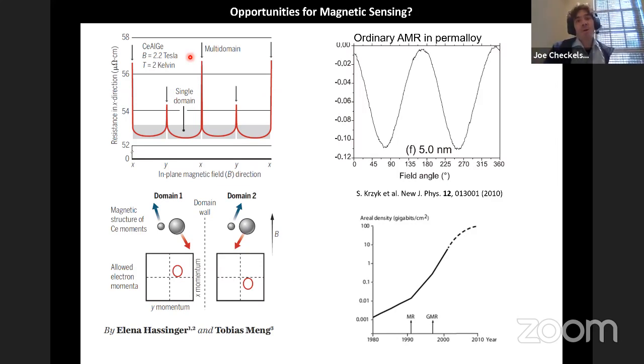If you look at how ordinary magnetic systems behave, typically you have smooth sinusoidal responses, for example, in this magnetic permalloy to external fields. What you could imagine is that in principle, what you could build here is a new type of way of doing vector magnetic sensing. So if you want me to say something crazy and unrealistic, imagine growing this material on the surface of a sphere or something like that, right? And basically what you would be able to do is pick out the vector orientation of a magnetic moment. So that's a fundamentally different way of doing magnetic sensing.